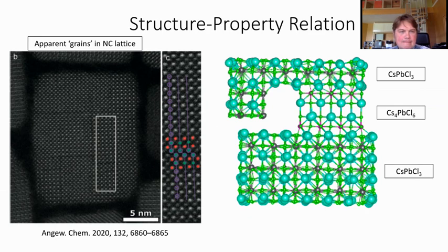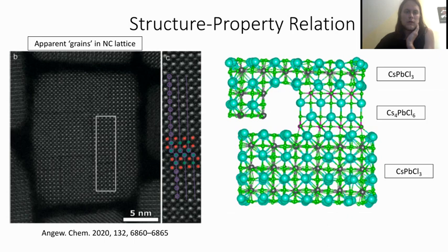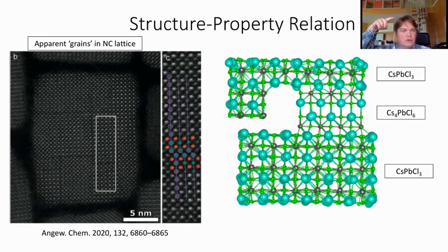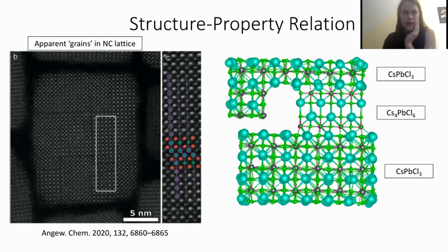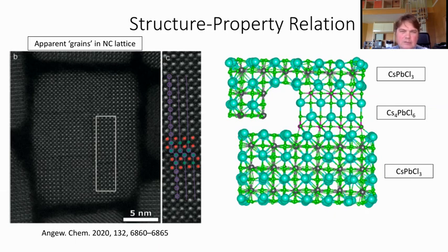It'll be slightly red shifted. Wait. Why red shifted? If there are layers, they increase confinement and energies increase, so go to blue, right? Oh, okay, yeah. So, the exciton or the nanocrystal peak. Mm-hmm. So at first I thought you meant, because people attribute the redshift of the dopants to aggregation of manganese too. That's what I thought you were saying at first. Okay, I see. So there are multiple dimensions. There are optical properties of manganese itself that change in aggregated and non-aggregated forms. And there are optical properties of the bands associated with intrinsic perovskite.